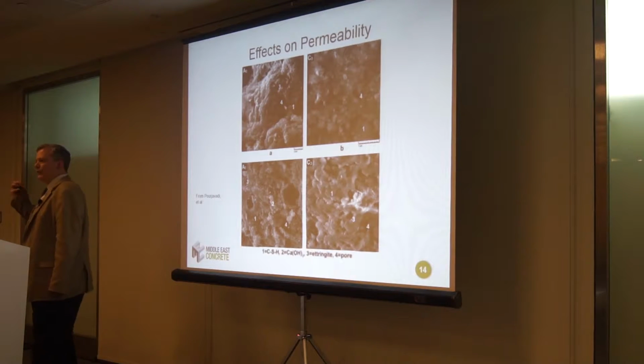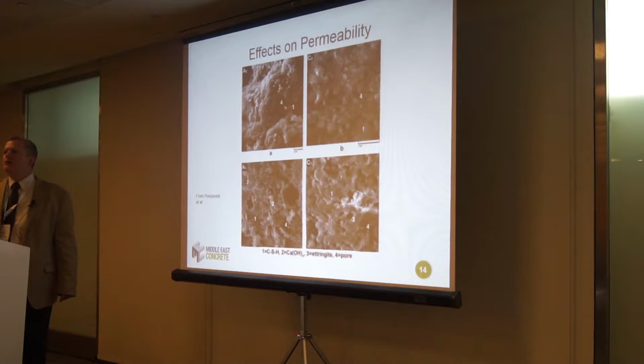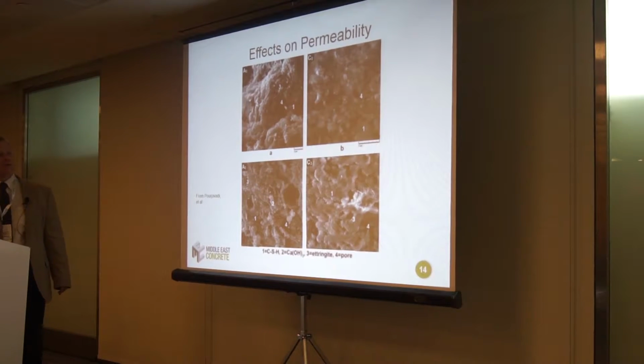So you can see that filling of capillary voids is something that you can see under scanning electron microscope, the filling of capillary voids from colloidal nanosilica. Now, does it have an appearance that will jump right out at you and say, hey, that's caused by colloidal nanosilica? No, it doesn't, because the colloidal nanosilica's reaction product is the same as what normally happens in concrete. As concrete gets hard, the water and the cement react. Calcium silicate hydrate is formed. Well, the calcium silicate hydrate is the reaction product between the calcium hydroxide and the colloidal nanosilica. So when we look at it under a microscope, the key indicator is that the pore space is greatly reduced, rather than something jumping out and saying, hey, I'm caused by this colloidal nanosilica.